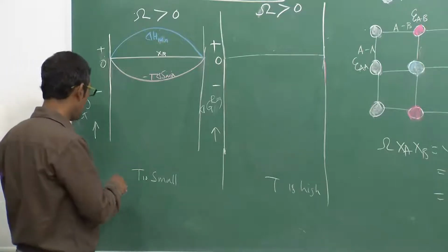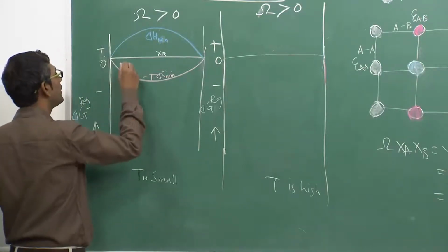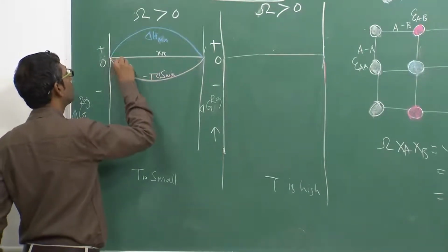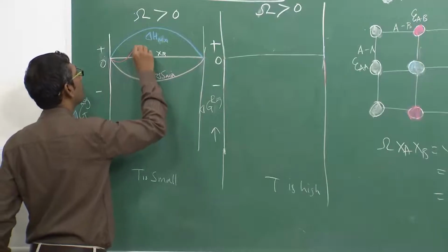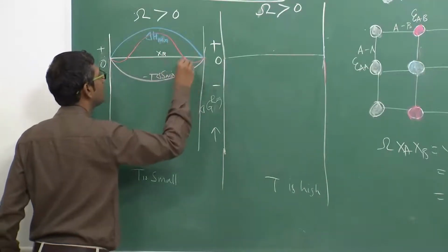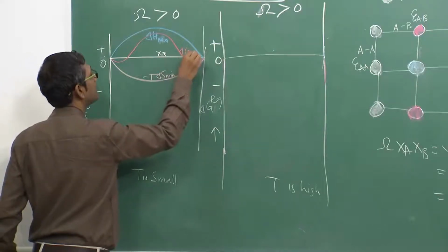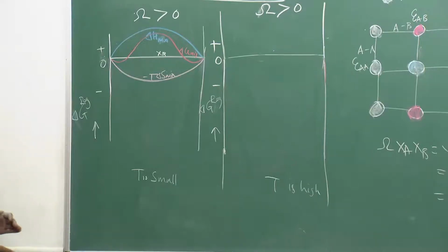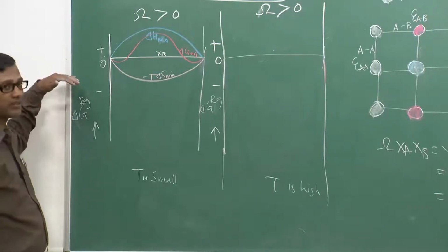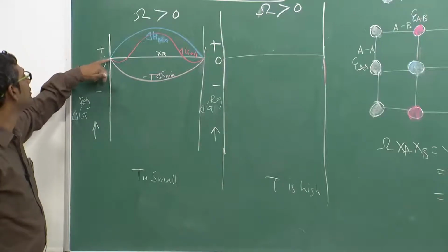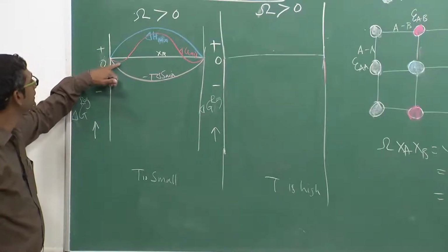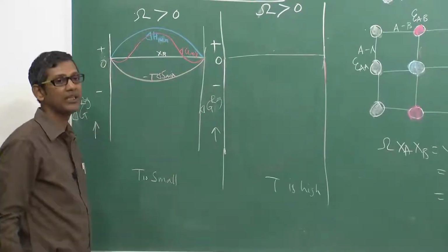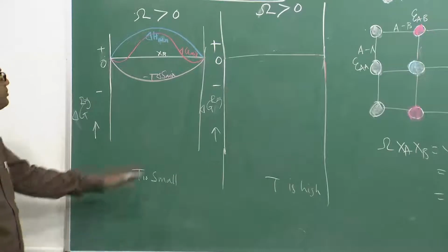So, this value will be a little bit higher, and therefore the negative contribution is more. So, it will go down and up, and it will be like this. That is my delta G mix. So, delta G mix starts at 0, goes down, then again increases, reaches a maximum value and decreases, and then again becomes 0 at XB equal to 1.